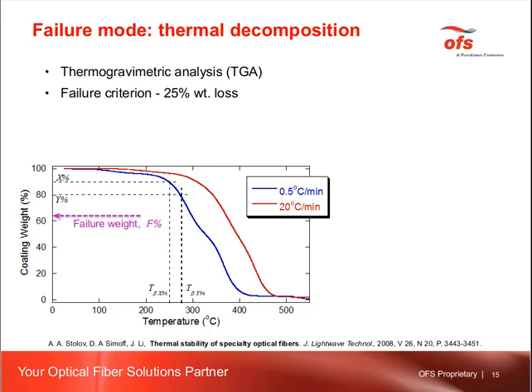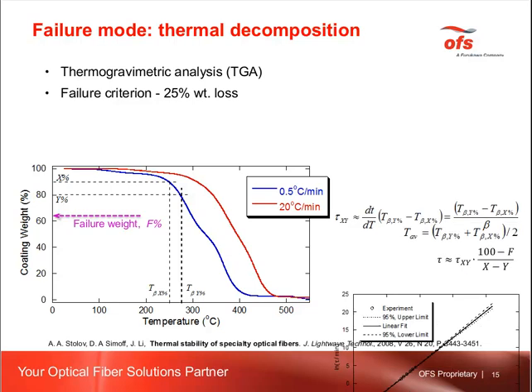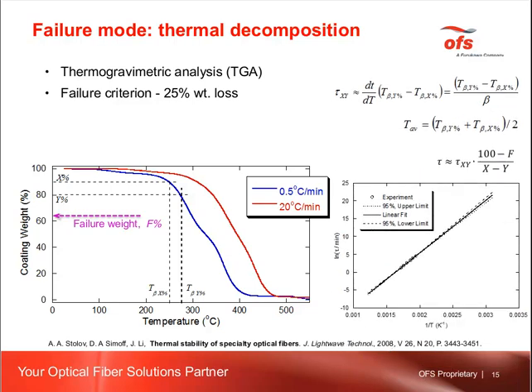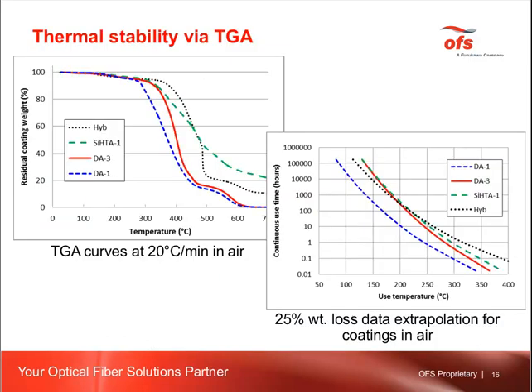The TGA experiments can be performed at different heating rates, and using some equations we can determine the times and the temperatures that correspond to this 25% weight loss achieved by the coating. This data then can be plotted in Arrhenius coordinates and extrapolated to other times and temperature conditions. On this slide, on the left-hand part, you can see examples of the TGA curves obtained for different coatings, and you can see that these curves are different. They can be used as a fingerprint for different coatings.